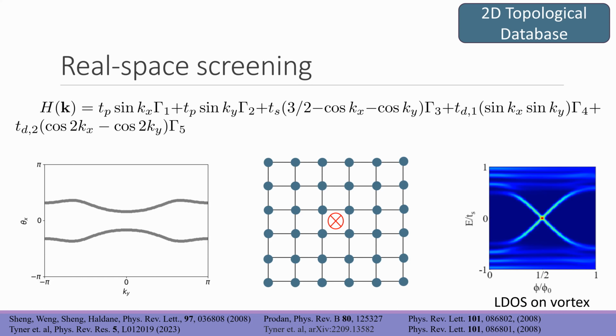We want to probe for bulk topology in this model, and one way we can do that is by inserting a magnetic flux tube. If we do that in this model, we see almost exactly what we saw before: the flux tube binds a single Kramers pair. So this is a really nice, clean way of probing for bulk topology that is non-symmetry-indicative. There is a method we could have used in momentum space.